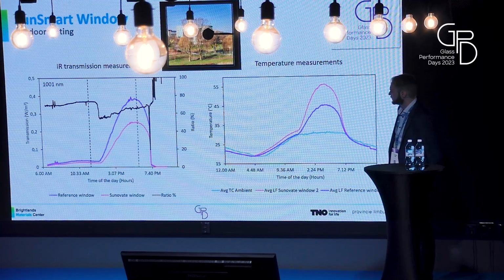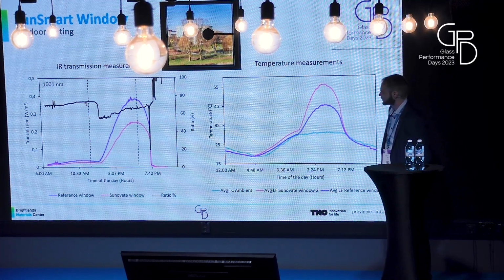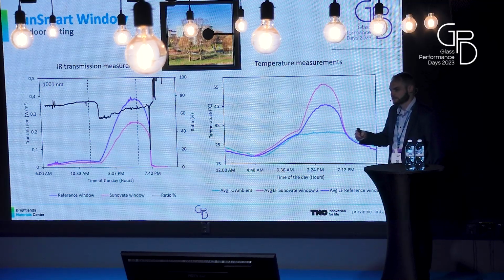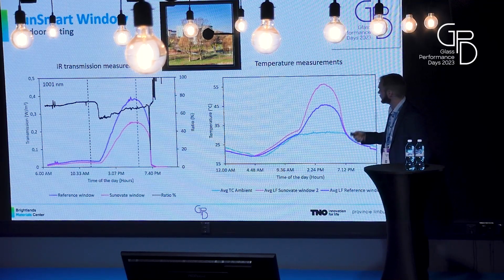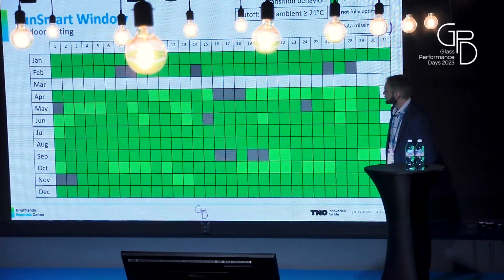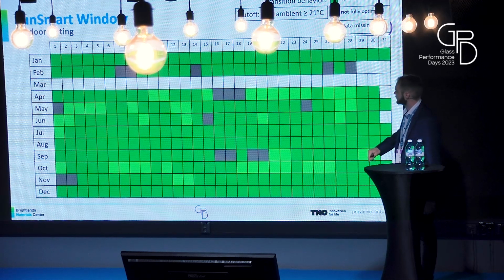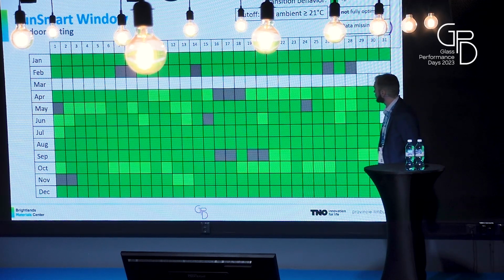And with all this data, we can then analyze all the days of a year, what kind of temperatures we have on the outside at the window, but also in what kind of state the material is. Does it switch or doesn't it switch? And then we can make an interpretation. Does the window function as we want it to function? And here we just set an arbitrary cutoff value at 21 degrees,